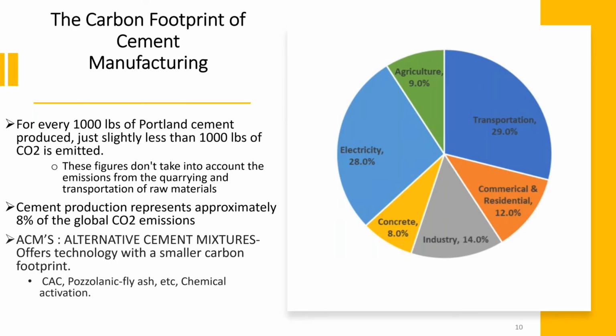The carbon footprint: I mentioned a minute ago that OPCs have a high level of contribution to CO2 due to how it gets processed in the kiln. If you look at it on a pie chart basis, 8% of total CO2 emissions comes from concrete, or actually the manufacturing of cement. And that doesn't include the traffic of cement to a job site or a plant for processing. Alternative cement mixtures, ACMs, have a smaller footprint, and I think that's the direction we'll see in the future, more use of that for that reason alone, or even blends of CAC with OPC.